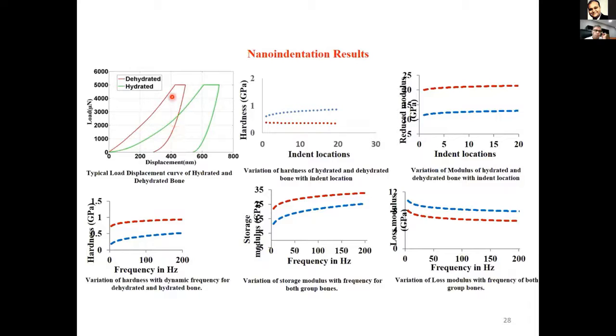So you can see that once bone gets dehydrated, its modulus and hardness increase, which is quite evident because of the water loss. The viscoelastic properties, so the frequency-dependent properties, also change in the case of dehydrated bone, and it is very important to keep in mind that the bone should not be dehydrated.